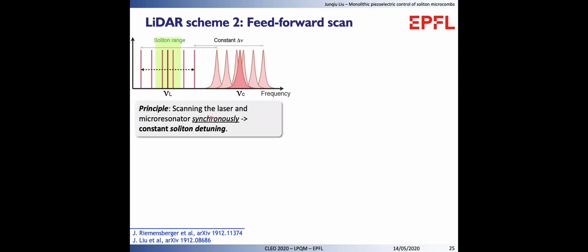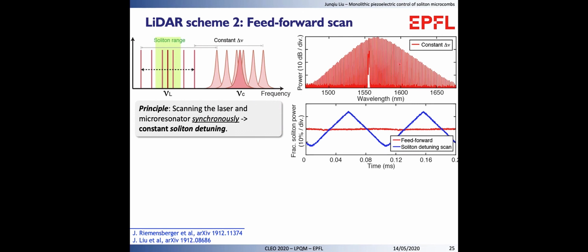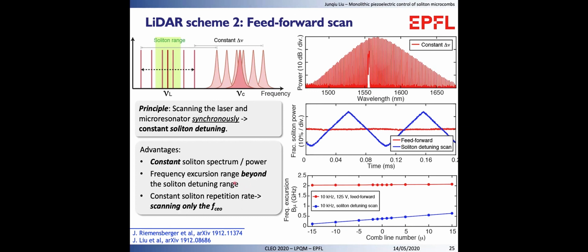The second scheme is feed-forward scanning, which is a better solution. In this case, the laser and the resonance are modulated synchronously, such that the soliton detuning is constant. As a result, the soliton spectrum and the pulse power are constant during the scanning. In addition, the frequency excursion is no longer limited by the soliton existing range, and it can go significantly beyond. Furthermore, free from the Raman self-frequency shift, the soliton repetition rate is constant, and each comb line has the same frequency excursion, as shown here. This scanning scheme is superior as it manifests as a scanning of the carrier envelope offset frequency of the microcomb, the FCEO, while the comb repetition rate is unchanged.